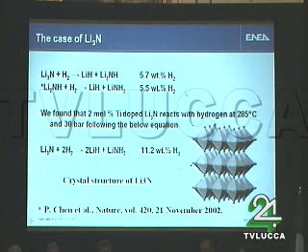It was shown that lithium nitride can reversibly cycle about 5% of hydrogen at 285 degrees, and we found that by doping lithium nitride with titanium at 2 mole %, it's possible to cycle about 10% of hydrogen per gram of lithium nitride.